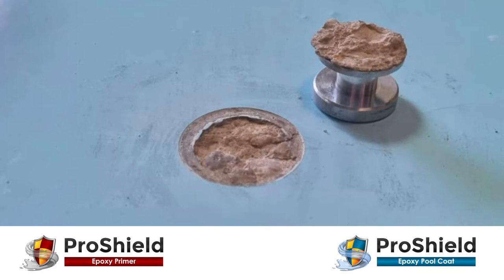The result of this test clearly demonstrates that the interlayer strength of the epoxy layers and the bond strength of the primer to the concrete exceeds the breakage level of the concrete surface. 2 to 3 millimeters of the concrete broke loose under the pull-off strength test at approximately 2 newton per square millimeter.